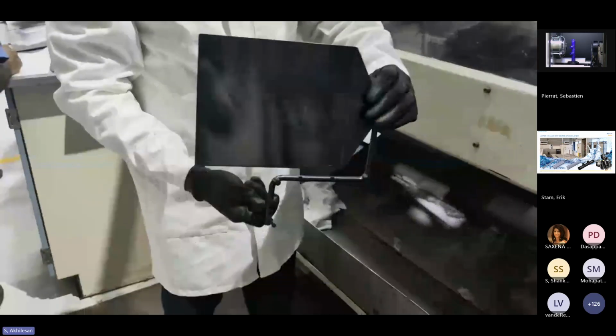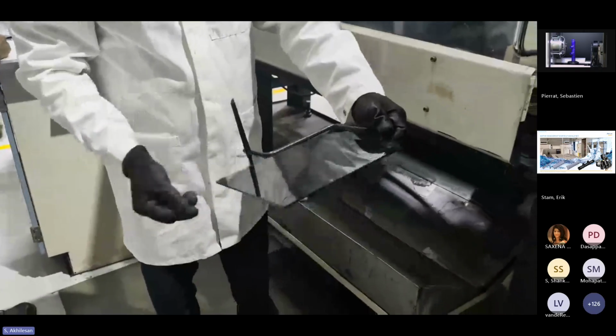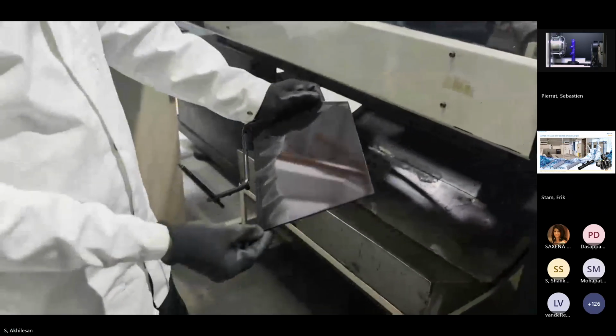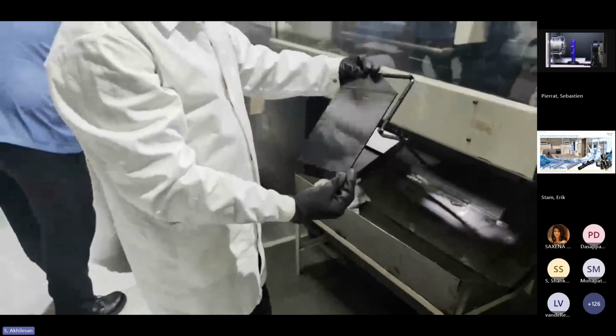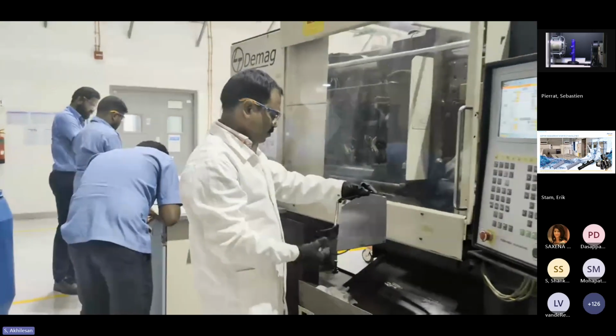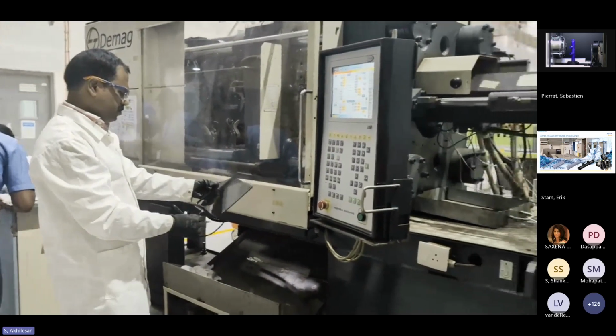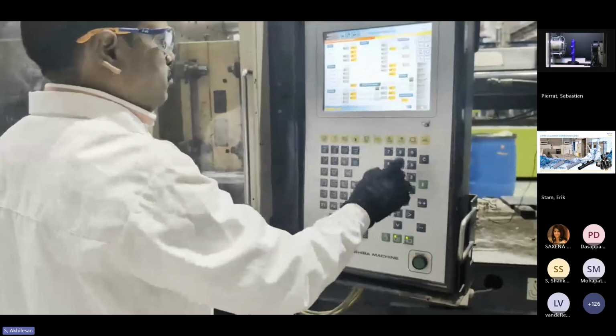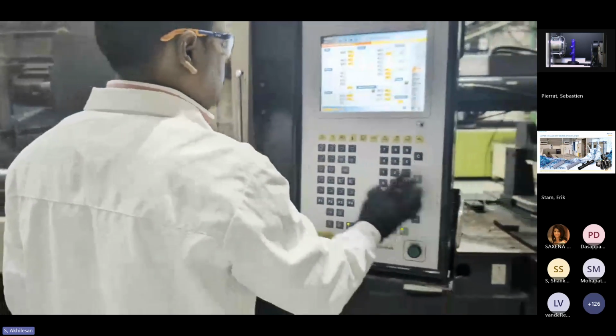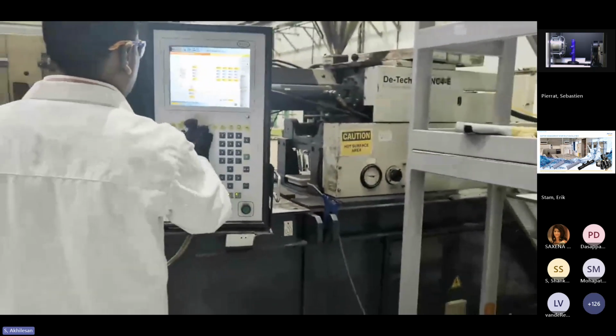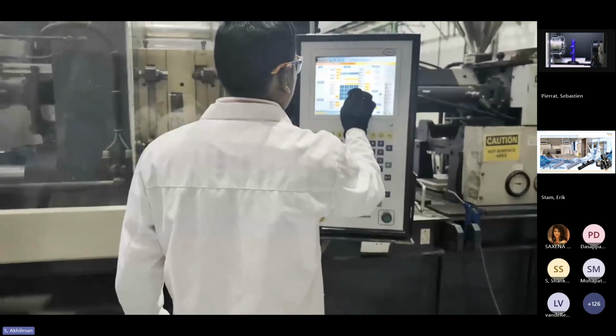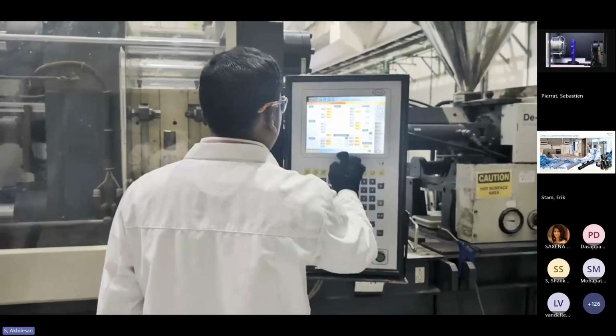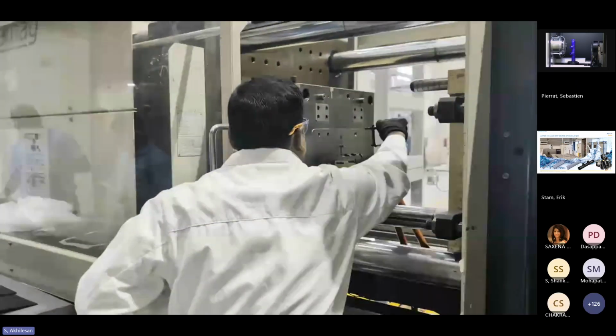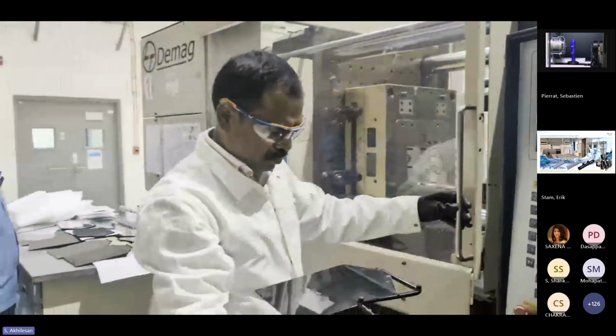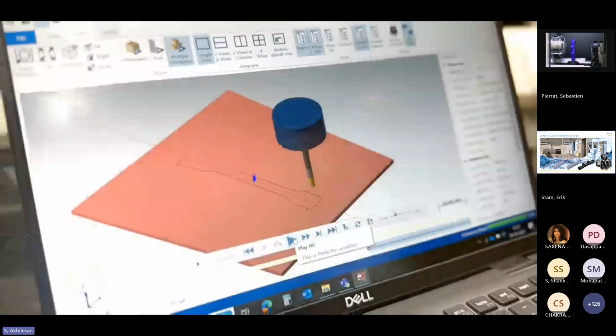This is our injection molding shear plaque that you can see here, which is with a cold runner. Now, typically for establishing good anisotropy in such a shear plaque, we need to fill it as slow as possible. And while setting the process parameters during injection molding, make sure to follow the recommendations set out on the TDS. And once the injection molding is completed, make sure that across shot to shot, there is consistency and the part is free of defects so that we do not introduce any other artifacts.